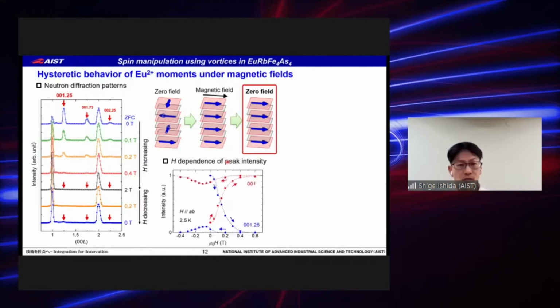The field dependence of the 00 1.25 peak and 001 peak intensity is reported in this figure. In the field decreasing branch, the intensity of the 001.25 peak recovers only partially at slightly negative field, where ferromagnetic and helical elements are expected to coexist in the sample.